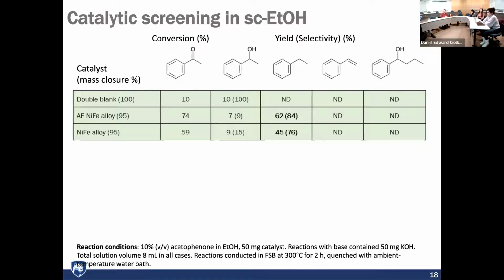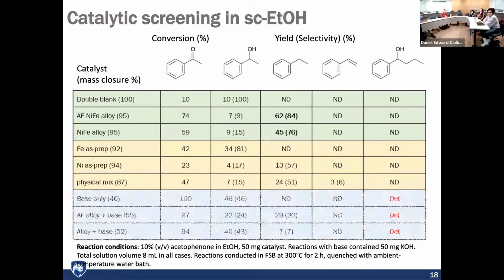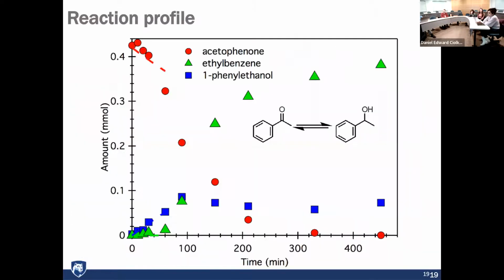So what we're looking at is how much of this turns into something else. That's conversion, right? So when we do with no catalysts, about 10% of this goes away and turns into other things. And in fact, it turns primarily into this thing. But when we add our catalysts, we'll see that here's our alloy catalyst, for example. 97% of this now turns into something else. And it turns into a mixture of these two things. 1-phenylethanol, which is the one that we want with the hydroxyl group, and ethylbenzene, which is one where the oxygen totally goes away. So we're trying to use these model compounds because it's more easy to track what's happening than if we just started with lignin, to try to see if we could get any information from these reactions.